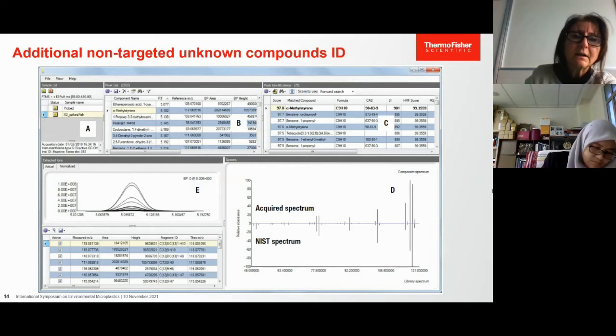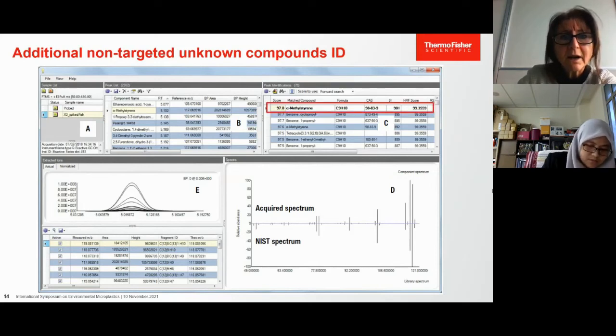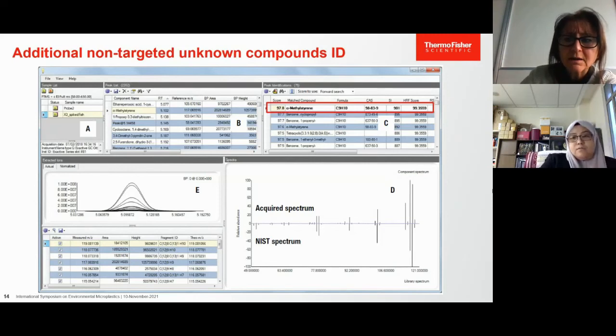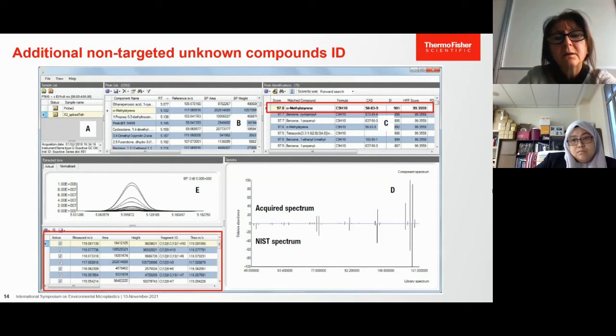In this slide, you can see the TraceFinder deconvolution browser showing the tentative identification of the alpha-methylstyrene based on the NIST library matching with a reverse search index higher than 900. So very good identification matching. And also the fragment rationalization with a confidence score that is higher than 99%. And here you can also see the mass accuracy is less than 1 ppm for the measured fragments from the deconvoluted mass spectrum.